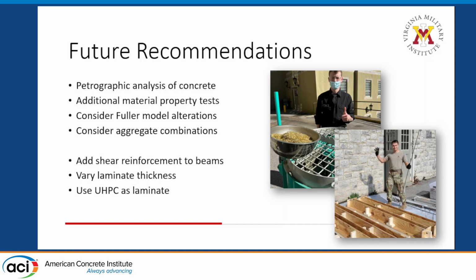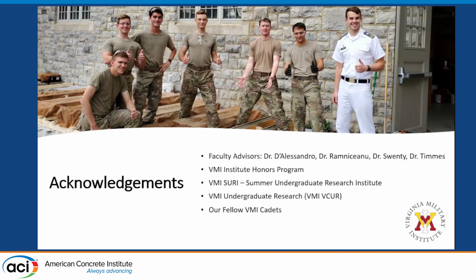Like I stated before, if we added shear reinforcement, we'd be able to see that increased moment capacity that we calculated for, demonstrated during the tests. For future recommendations on this side of the research, I recommend, instead of focusing on the location of that laminate like this project did, you vary that thickness, find that optimal UHPC thickness, and this time you use commercially provided UHPC. That way you know exactly what mix you're using. It's not so experimental like in this case. And here's some of the people that helped us out during our project.